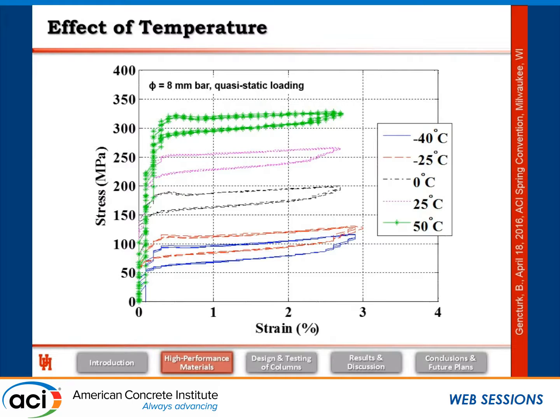The other thing that we looked at is the temperature dependency of this superelastic behavior. This was a quasi-static test, because we wanted to exclude the effect of the strain rate. We tried here 5 different temperatures from minus 40 C all the way up to 50 C. As you can see in this graph, there's quite a dependency of the superelastic behavior on the temperature. Under normal conditions, room temperature is about 25, let's say, you see this behavior with about 250 MPa yield stress, and then if you increase the temperature, you go up, and if you decrease the temperature, you go down.